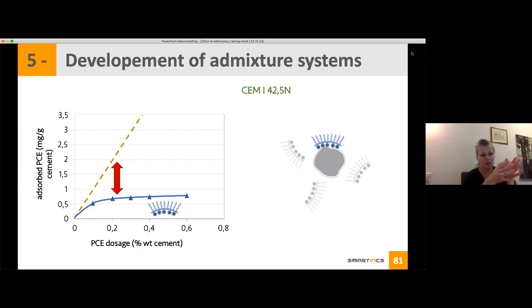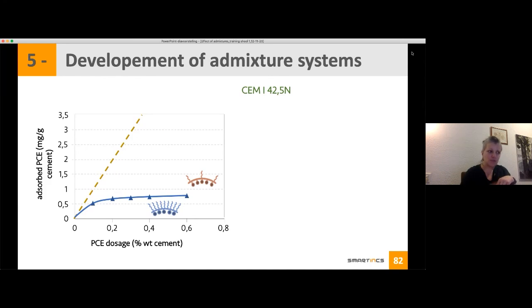I try to schematize it on the right. You have my cement particles. I have my admixture, but only a small fraction is adsorbed on my cement particles, and the rest is in the pore solution. So it means that I have only a small fraction that is used for the dispersion of my cement particles. At that time, the others do not have any effect or function for the dispersion. So then I say, okay, I will try another PCE. I will try this one, and this is what you get. So you see here that the behavior between these two is different.